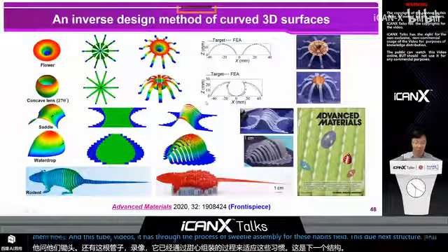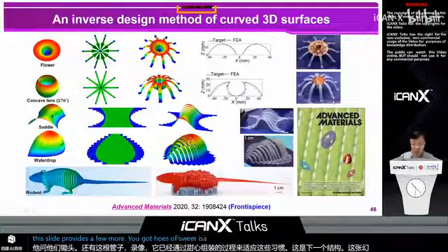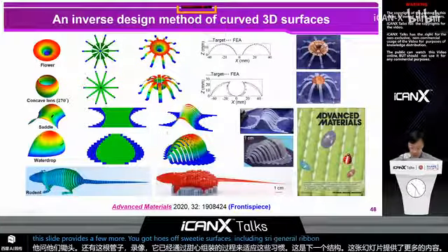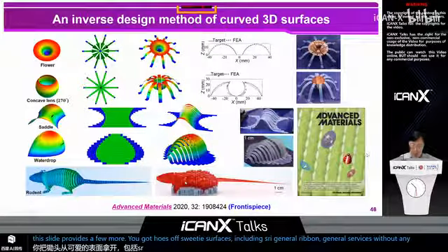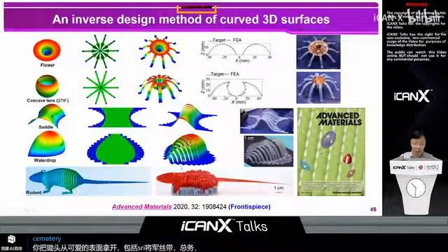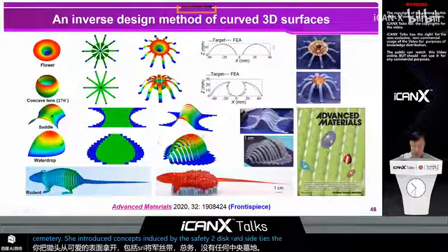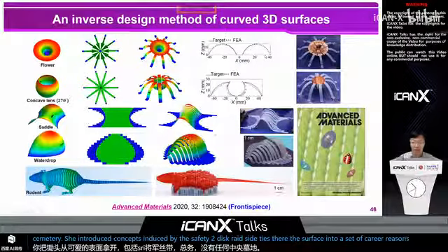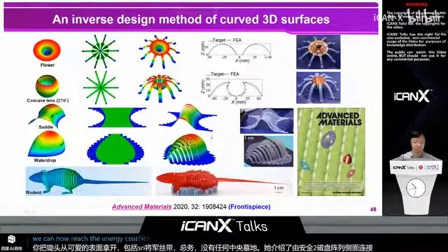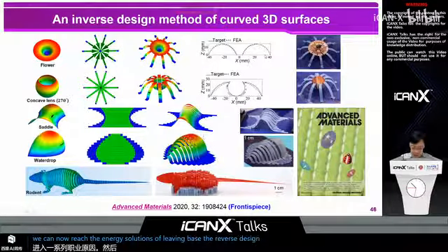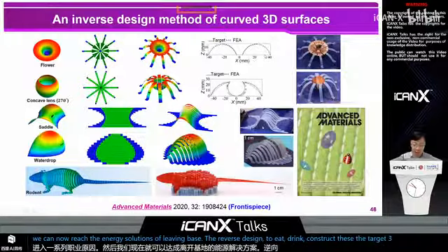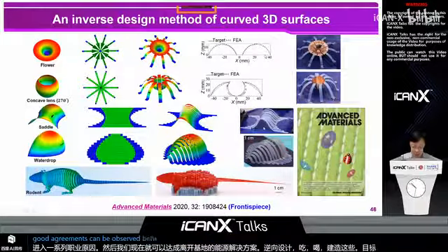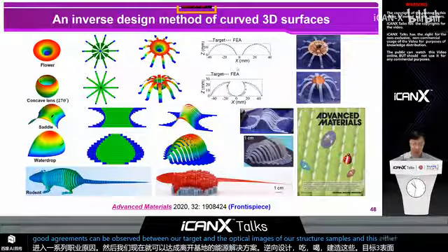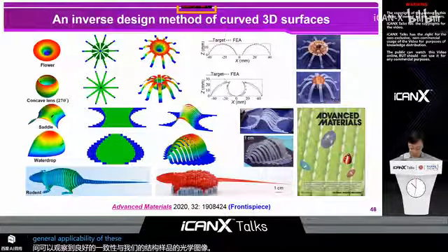And this slide provides a few more examples of 3D surfaces, including three general surfaces without any central symmetry. Here we introduce concepts induced by the CT to discretize the surface into a set of curvy ribbons. And then we can leverage the analytical solutions of ribbon-based inverse design to reconstruct this target 3D surface. And good agreements can be observed between our target and the optical images of our structural samples. And this illustrates the general applicability of this inverse design method.